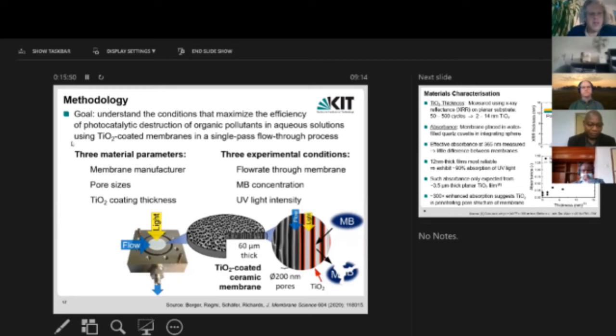So we're varying 3 material parameters, as we call them. 2 of them we don't have a great degree of control of. There are 2 suppliers of the membrane, and 2 different pore sizes of the membranes available from each. And then what we do have quite good control over is the titanium dioxide coating thickness.